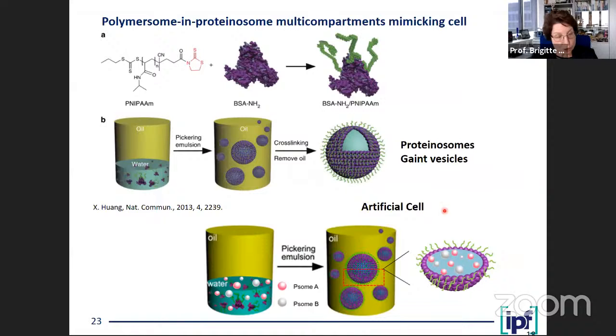So for that, we need a larger compartment. The polymersomes we prepare so far by the self-assembly process are limited in size. We can control it a bit by the molecular weight, but not so much. But we have another tool, which we are developing in cooperation with Professor Huang in China. He is making biohybrids between a protein and PNIPAM, which is a thermoresponsive polymer. And by that, you get those biohybrids and you can assemble them into giant vesicles. Those vesicles are in the range of micrometers, even up to 20 micrometers. And we thought, okay, we'd use those giant vesicles as the outer compartment, like the cell membrane, and put some interesting polymersomes inside to have a multi-compartment system.